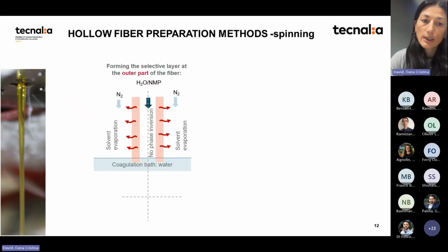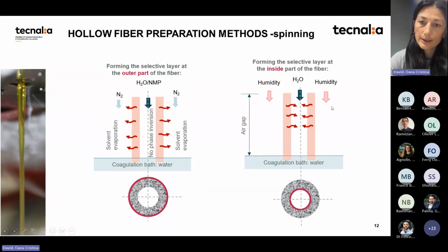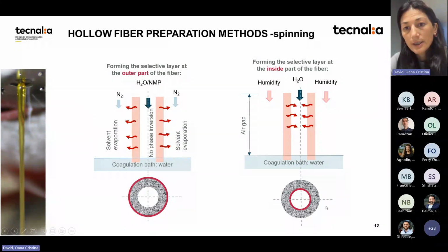We can also have the selective layer inside, and here it is represented in the second part, on the right side of the slide. In this case, we have water as coagulation liquid that can mix. The condition is for the water to mix very well with the solvent that is used for the polymeric solution. And then outside we have humidity. So here we would like to have an outer surface with a high porosity and an inner surface with a dense layer.